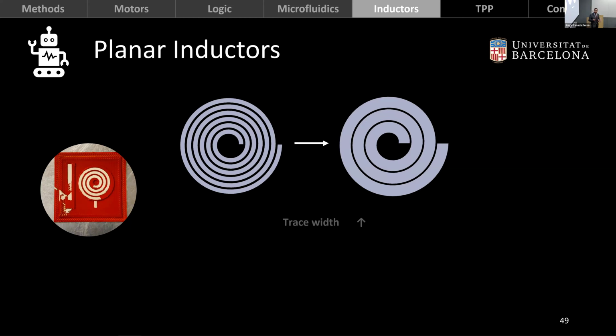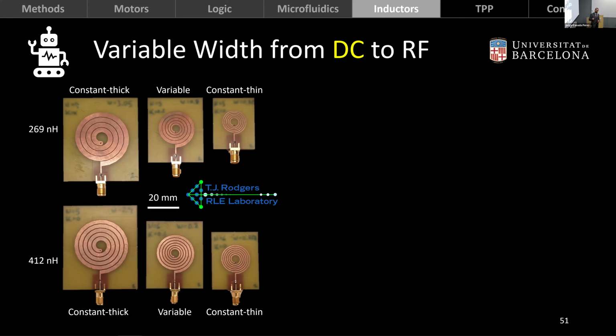And what we were wondering here is, can we use this in DC to improve the magnetic fields that we are getting, and what happens all the way from DC to RF. And so for that, we fabricated these inductors, again, with the help from the Rodgers lab. And we fabricated 2 sets, each set having the same nominal inductance. And in each set, there's 2 inductors of constant width, one thick and one thin, and one variable width inductor.